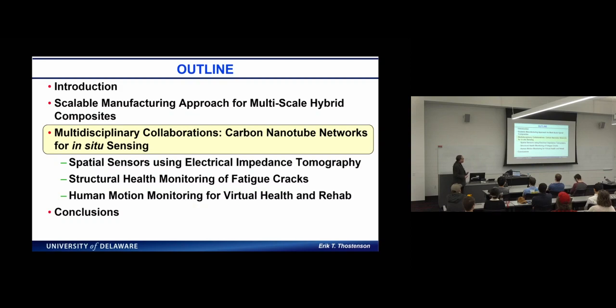We have a Department of Energy project looking at using electrical impedance tomography to not only have, instead of having a sensor where you measure something locally, we can actually map something. That's something, say, if you had a composite and then you have local damage, composite planes, there's a lot of them, they get struck by birds, right? So you can get delamination. And so this is what we want to do, is localize, not only that there's damage, but we want to localize that damage.